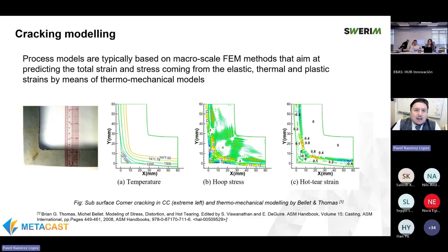Oh, yeah. So, cracking modeling. The process models are typically based on macro scale FEM methods that aim at predicting total strain and stress. I bring as an example this excellent publication from Professor Thomas and Professor Michel Bellet in France, that addresses the distortion and hot tearing. So here you can see the classic corner of a billet, and you can see the formation of a depression on this side, which is very likely responsible for this internal crack formation. And here you can see a good example of how FEM is used to predict this location, but we haven't got to the point yet where we can see open cracks in the calculations, although I'm sure we are going in that direction.